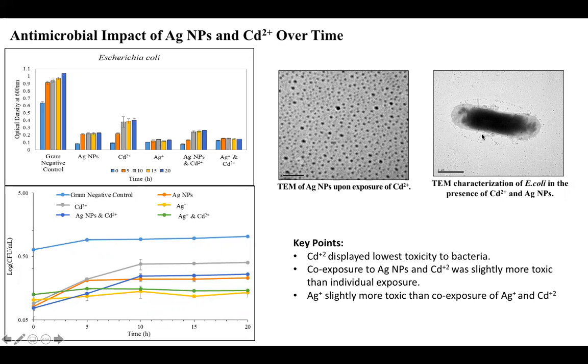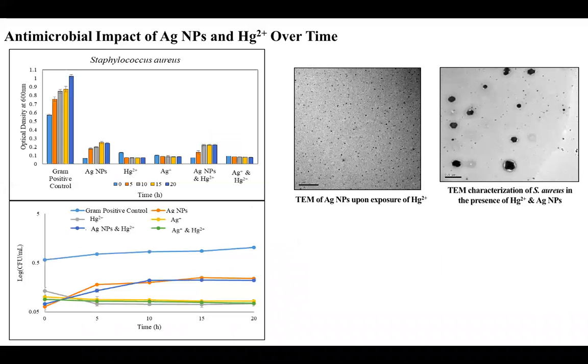And again, if we look at that cell of E. coli, we can see that these nanoparticles are concentrated all around that cell and starting to break it down, which we expect to see because those are the two pathways we want to see. But one thing that is interesting is there is a difference between the silver nanoparticles and silver ions. So that indicates that we're not only seeing silver ions at the surface, but there could be something else going on in how it's penetrating the cell that's changing that toxicity.